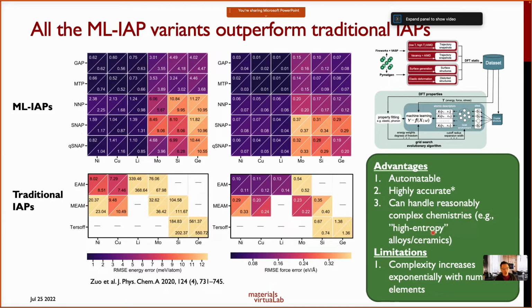and they can handle reasonably complex chemistries, right? So, for example, we have built machine learning interatomic potentials for high entropy alloys and ceramics. These are very, very difficult, if it's even possible, to get right with things like EAM and MEAM, right? Now, the limitation, however, is that the complexity increases exponentially with the number of elements, right? So up to about 5 elements, 6 elements, we can still build a machine learning interatomic potential for them, and we can get reasonably high accuracy, right? Once you talk about, well, can we build a machine learning interatomic potential that can encompass the entire periodic table, what we call a universal potential, you can't really do that with any of these formalisms out there, right?